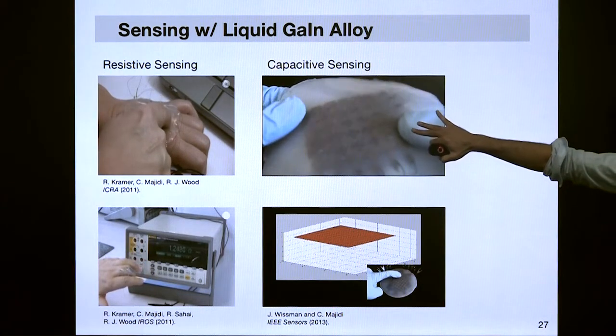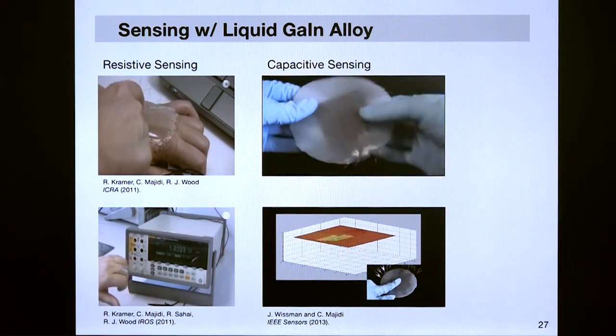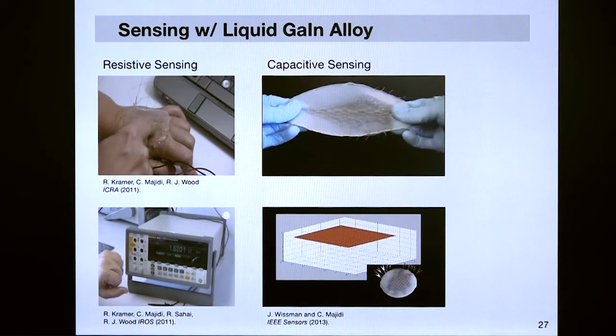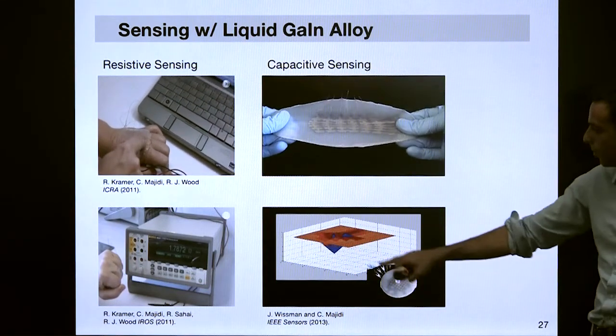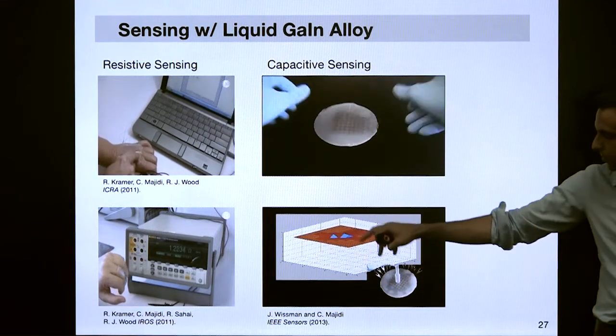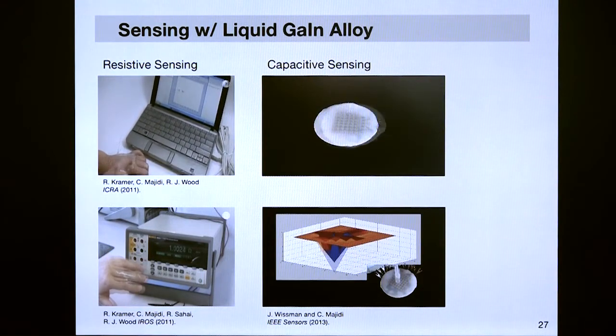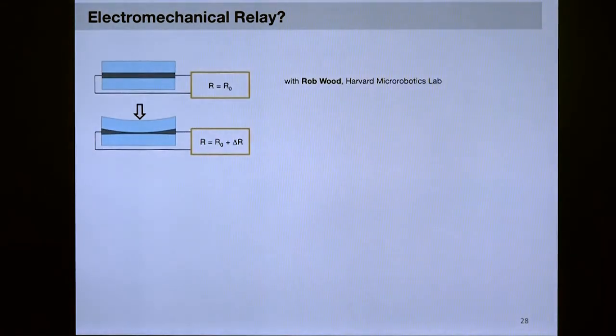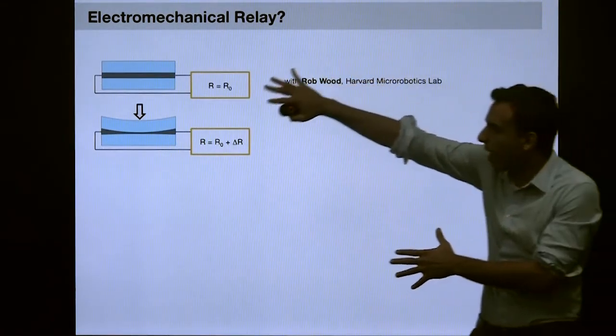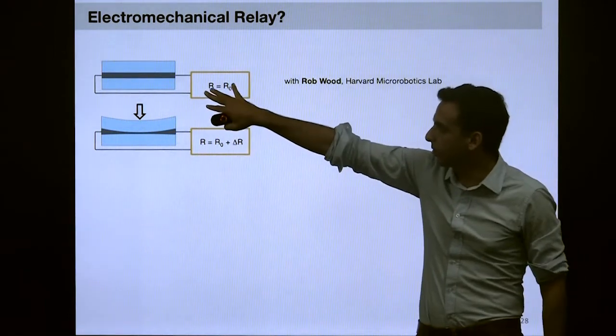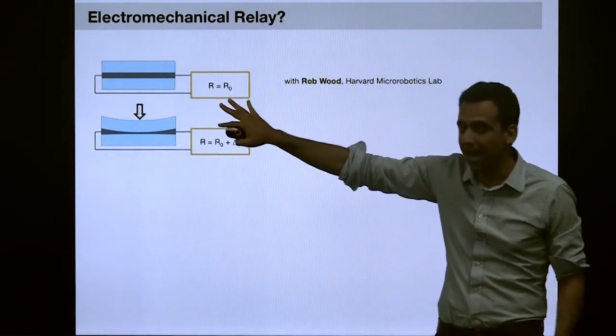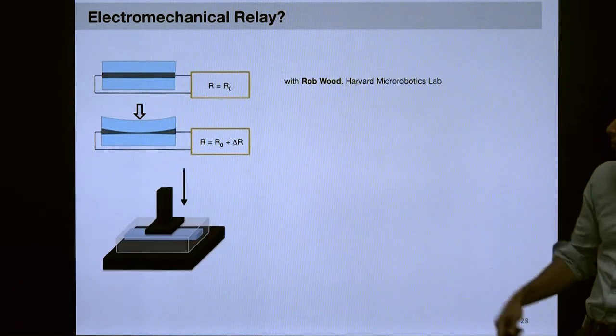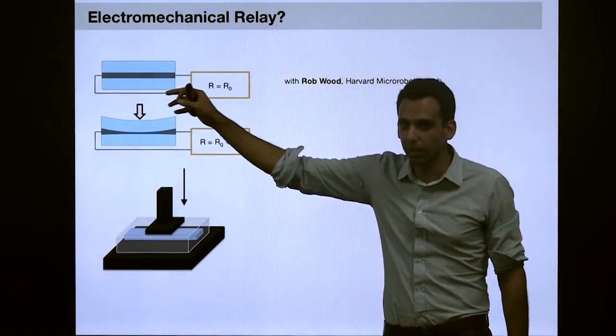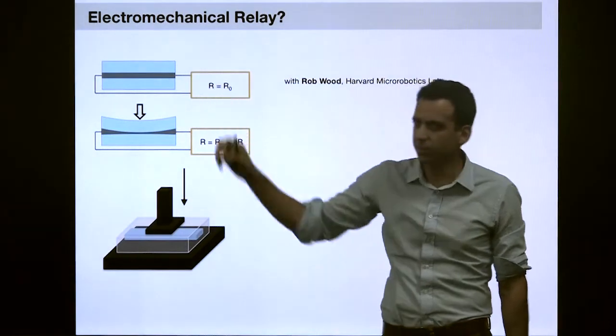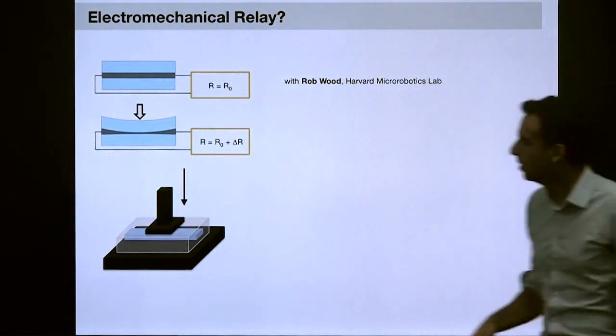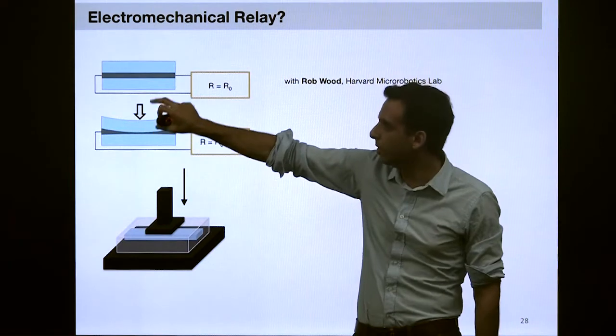The way I arrived at the pressure-electric resistance coupling was almost by accident. I was originally trying to create some type of electromechanical device, creating liquid metal channels. If you applied just a little bit of pressure on these channels, that was enough to collapse them, and you could have some kind of open and closed channel. But then when I started applying pressure with connectivity, you had an extreme amount of sensitivity. Let's apply up to say 100 pascals, and the resistance shoots up, and you lose connectivity. With a modulus of 125 kilopascals, we're talking very high sensitivity. It occurred to me that maybe this is not ideal as an electric switch, but as a sensor, right?